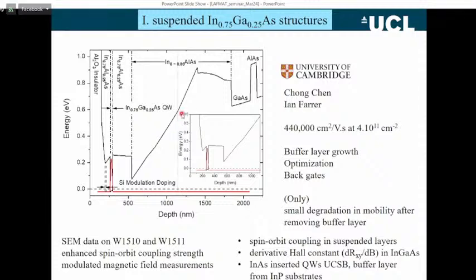However, what we've done recently is to completely etch away the substrate. So we make a device and we etch away all the material at the back. And we found that we don't degrade the mobility after removing this buffer layer. The buffer layer was originally put in to minimize defects, create a nice clean system, but we found we can take most of that away and do not degrade the electrical properties of the wafer.